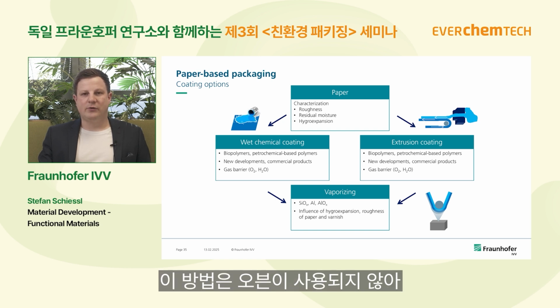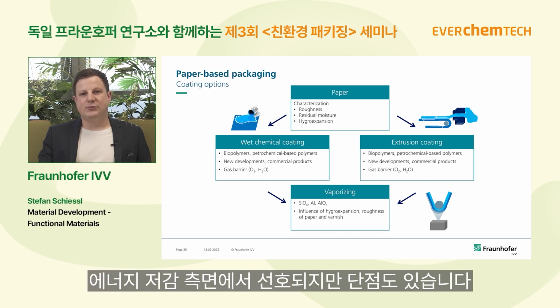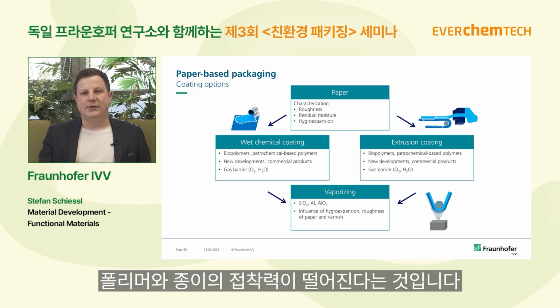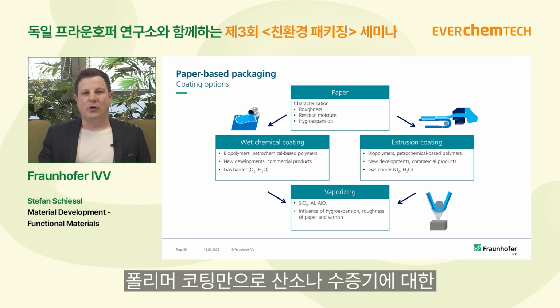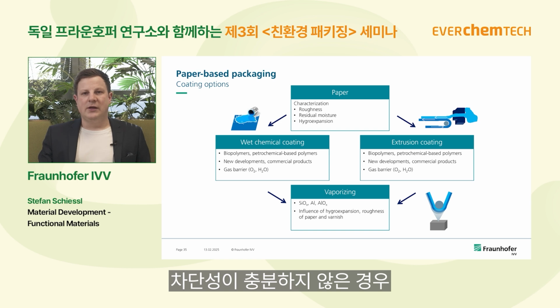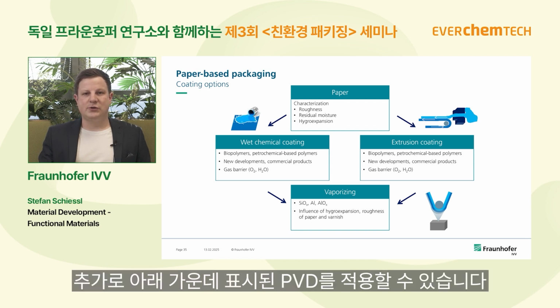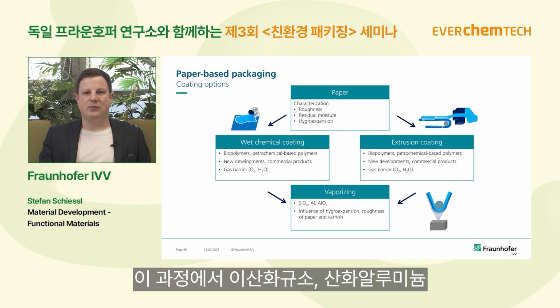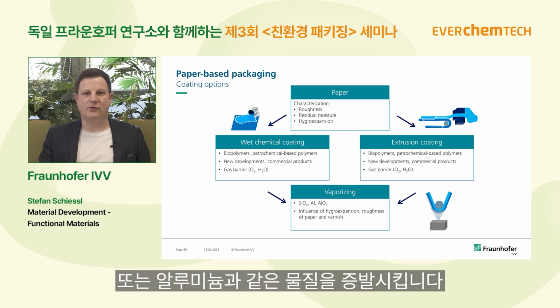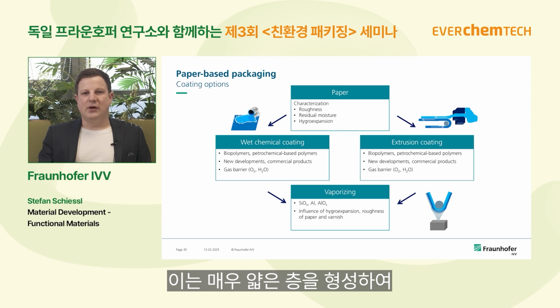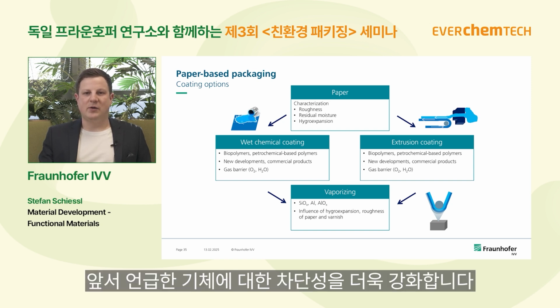This is, from an energetical point of view, favored, because you don't need the energy for the oven, but there are some disadvantages to this process. For example, the adhesion of the polymer to the paper. If the barrier you achieve by the coating with the polymers is not enough, for example against oxygen or water vapor, then we can additionally add a physical vapor deposition, which is shown in the middle below. This means you evaporize a material, for example silicon oxide, aluminum oxide or aluminum, and this is building a very thin layer that has even a better barrier against the gases we were talking about before.